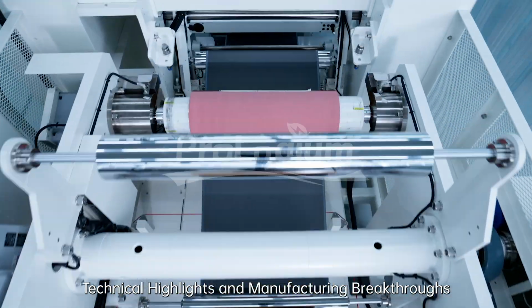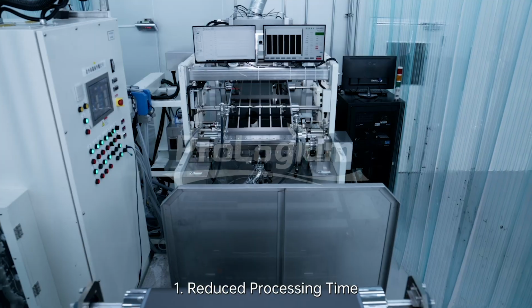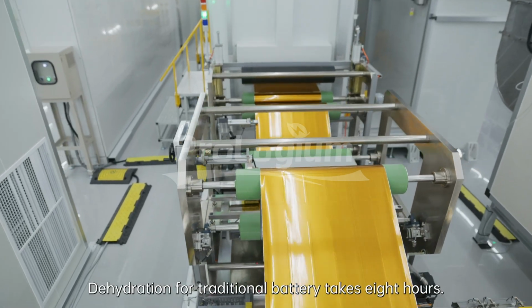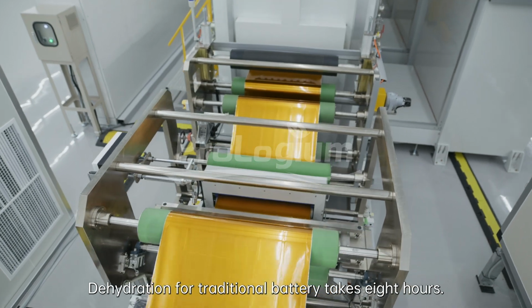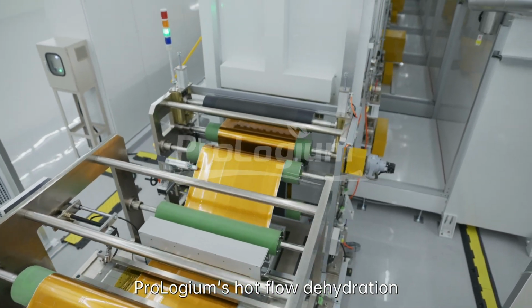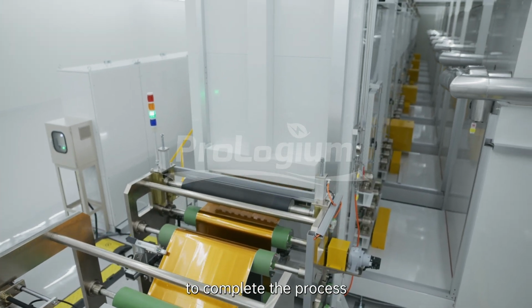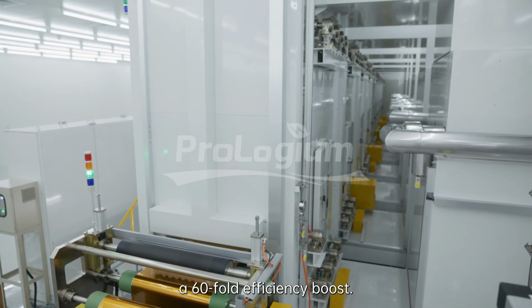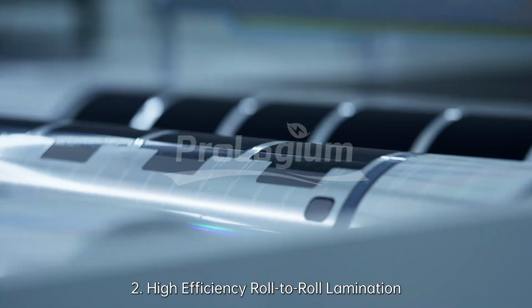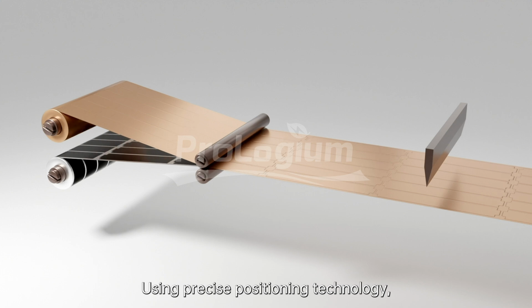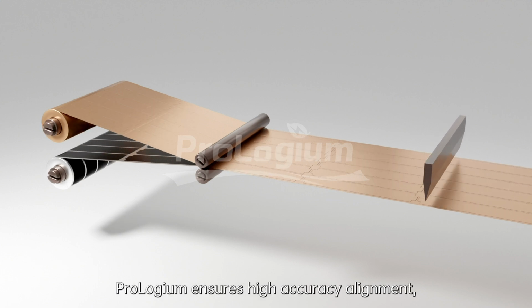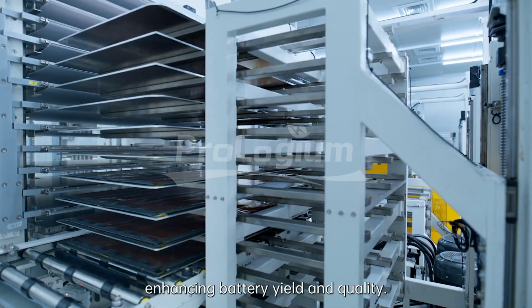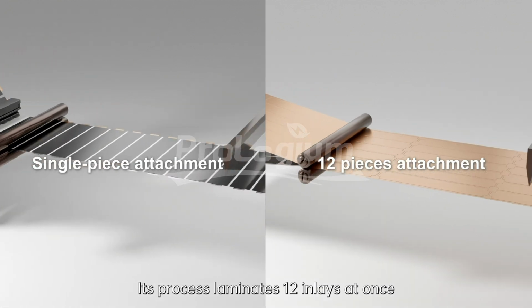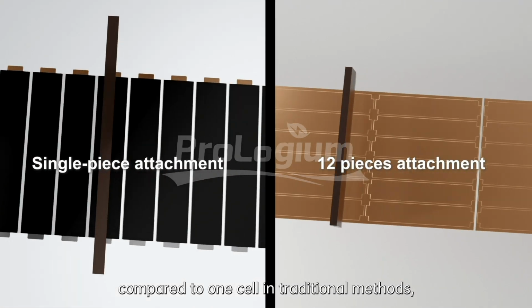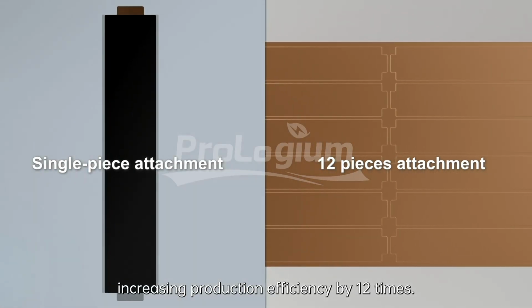Technical highlights and manufacturing breakthroughs. 1. Reduce processing time. Dehydration for traditional battery takes 8 hours. ProLogium's hot flow dehydration takes only 8 minutes to complete the process, a 60-fold efficiency boost. 2. High efficiency roll-to-roll lamination. Using precise positioning technology, ProLogium ensures high accuracy alignment, enhancing battery yield and quality. Its process laminates 12 inlays at once, compared to one cell in traditional methods, increasing production efficiency by 12 times.